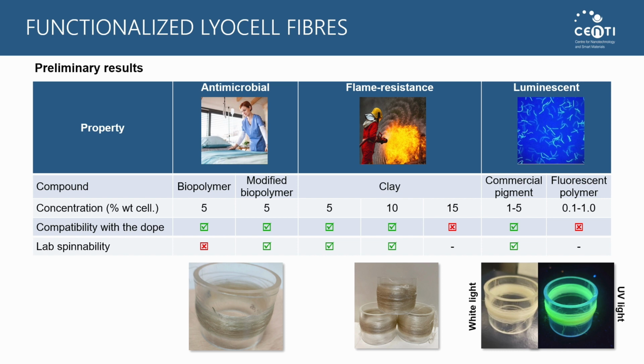For the antimicrobial fibers, we tried a biopolymer, and we had to make a modification on the physical size of this biopolymer to get good compatibility with the dope and also spinability into fibers.